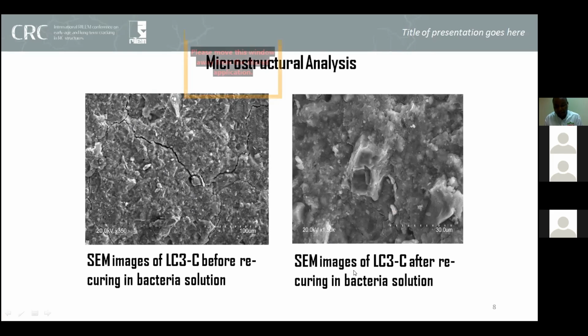After the samples were immersed in a bacteria curing solution, there was a degree of crack healing, and it was quite clear that the sizes of the cracks were greatly reduced after 90 days. This shows that there was deposition of calcium carbonate visible due to the bacteria precipitation process.